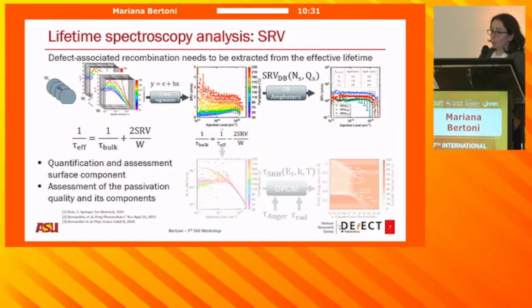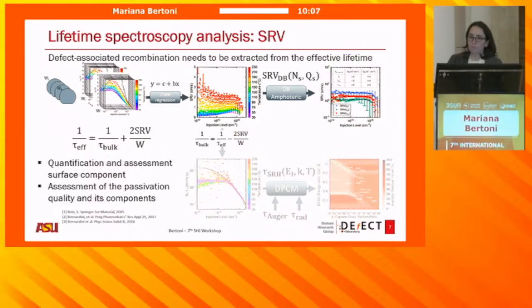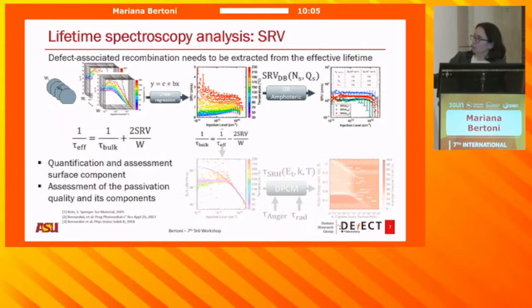And so there's a lot of samples in here. You're going to see a couple of points here and there, but these are many, many samples. Once you get your surface recombination velocity, you can use the amphoteric defect model, which basically has 3 different states for hydrogen, and you can actually fit your interface defect density and your charge density at the interface. If you fancy looking at the bulk, you can also take a look at the bulk, but that's beyond what we're going to be chatting about today. I'm happy to chat with any of you that are interested in it.